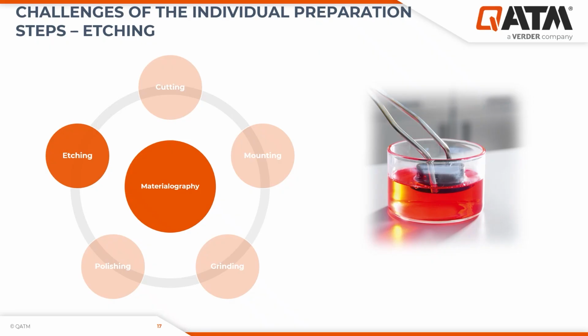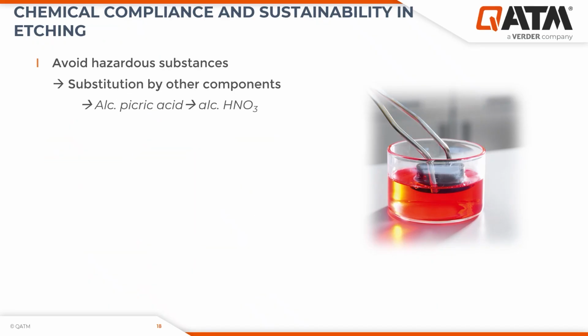There are usually three ways to try to improve on the chemical compliance when using etching agents. The first way is to avoid hazardous substances completely. So by substitution by other components, like we've seen in our other examples, you can try to, for example, exchange your alcoholic picric acid for etching purposes with alcoholic nitric acid solutions, which tend to, depending on the material that you're etching, result in similar etching performance and properties.